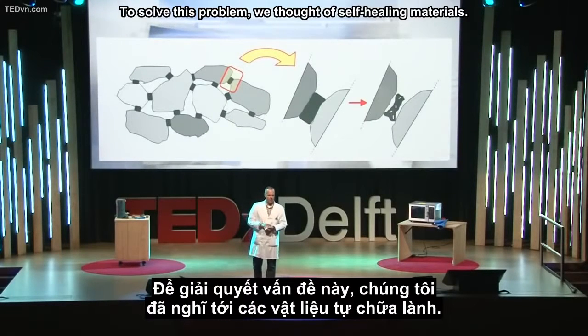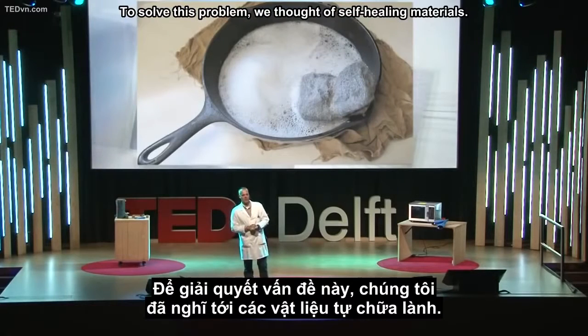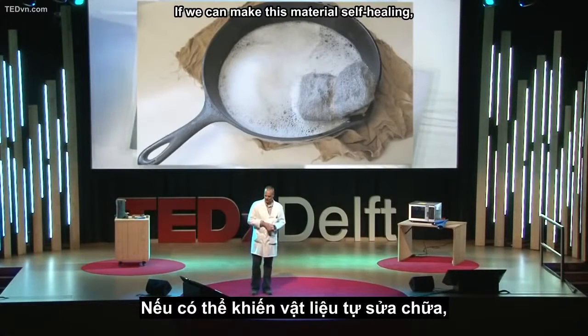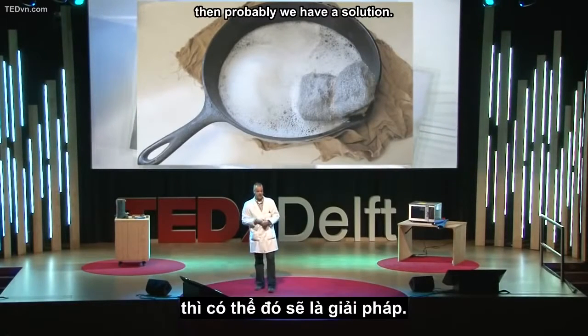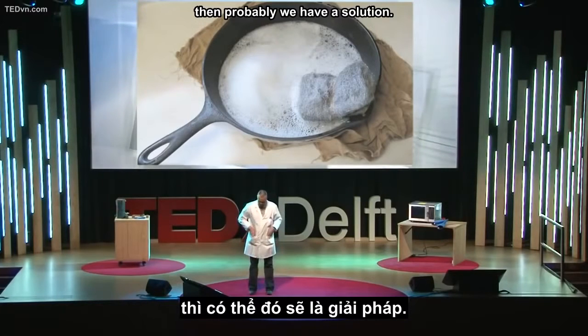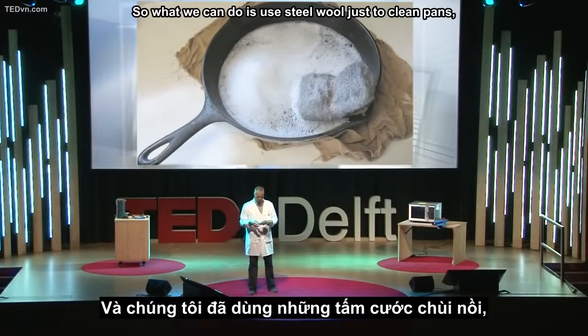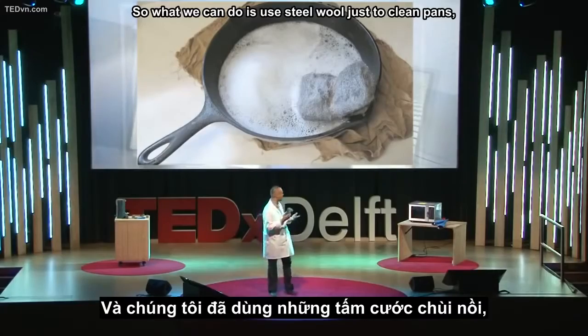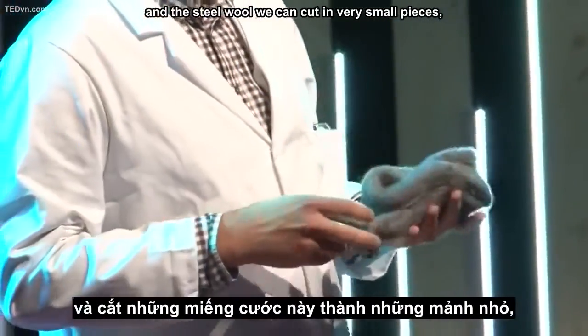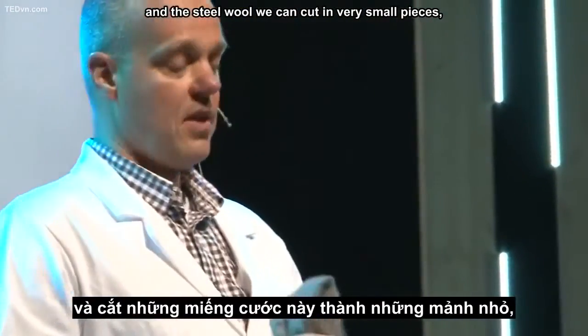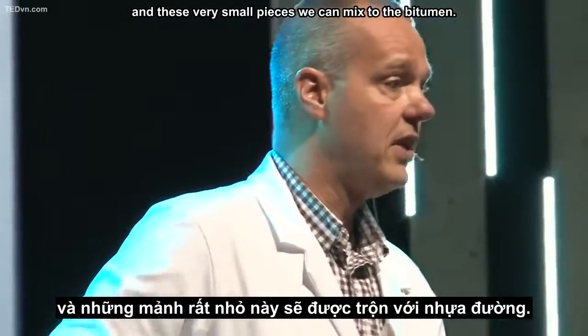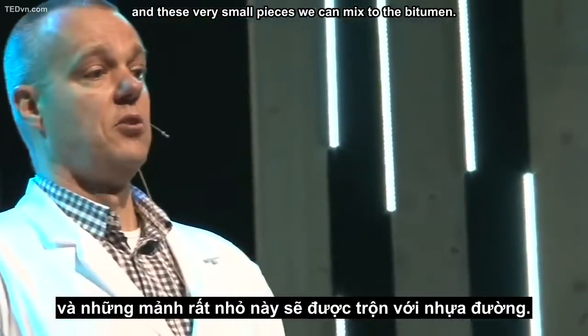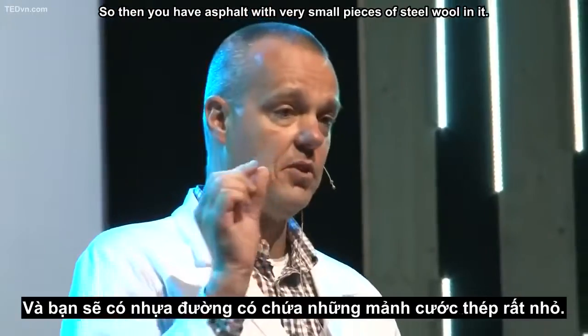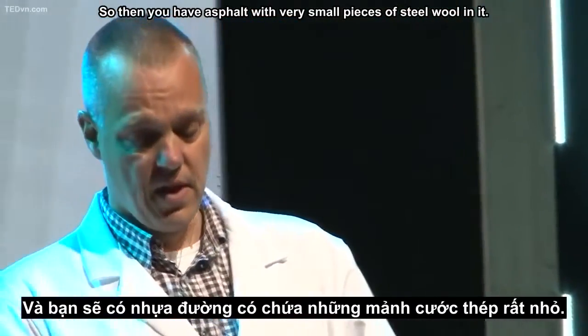To solve this problem, we work on self-healing materials. If we can make this material self-healing, then probably we have a solution. So what we can do is use steel wool, just like you use to clean pans. This steel wool we can cut in very small pieces, and these very small pieces we can mix through the bitumen. So then you have asphalt with very small pieces of steel wool in it.